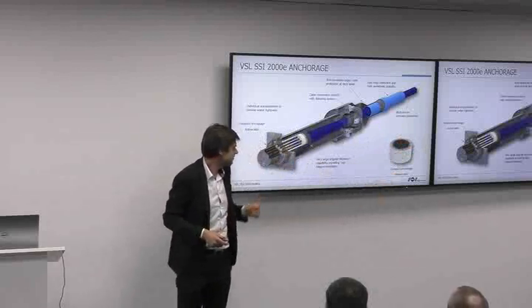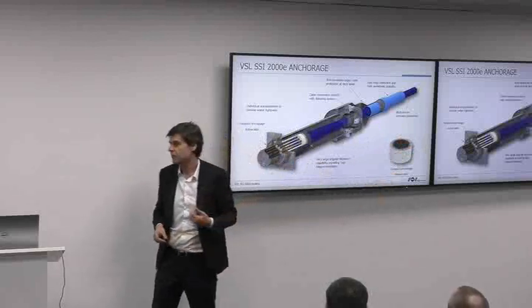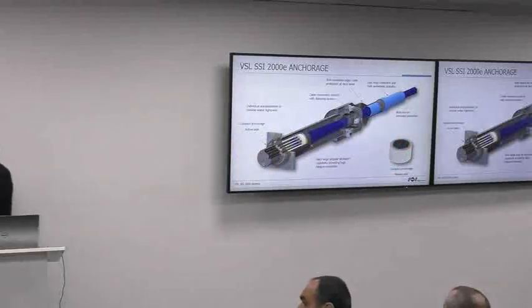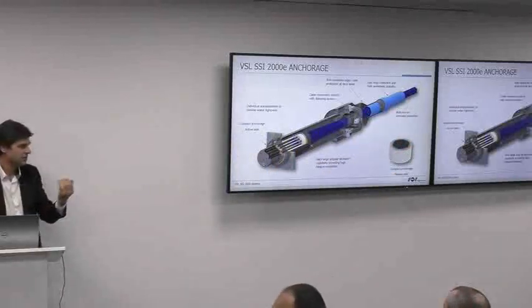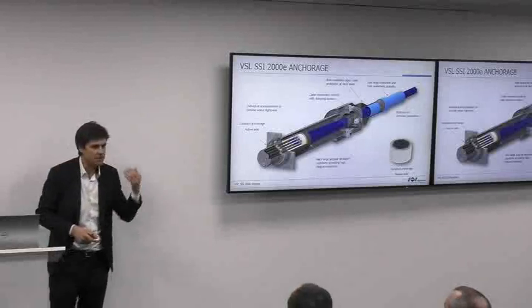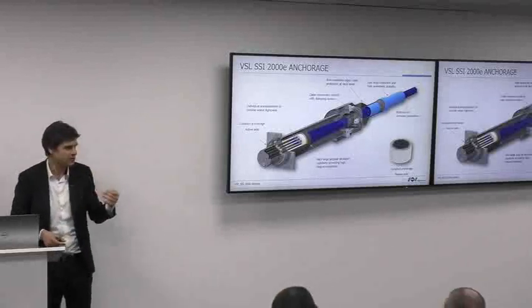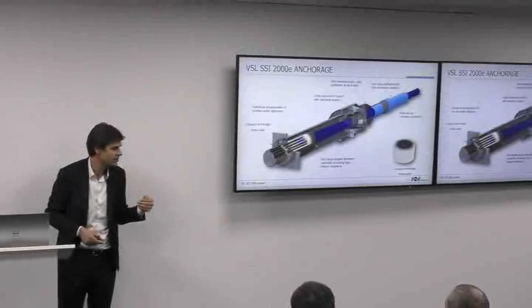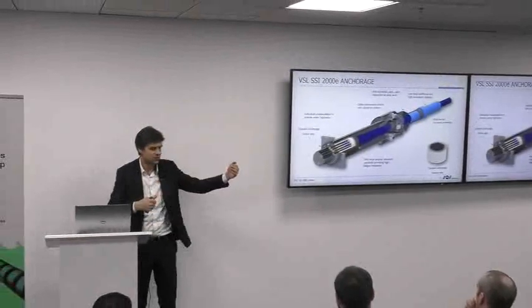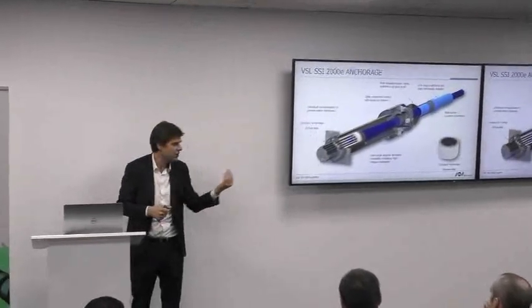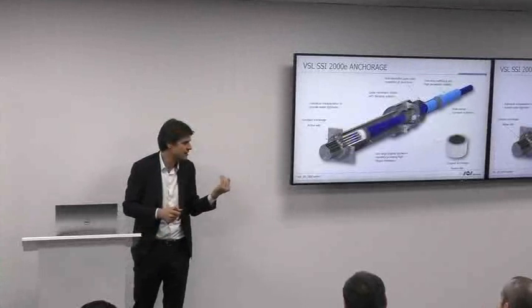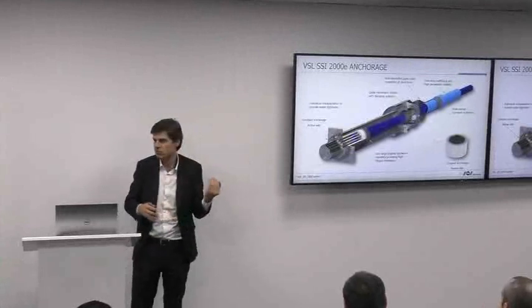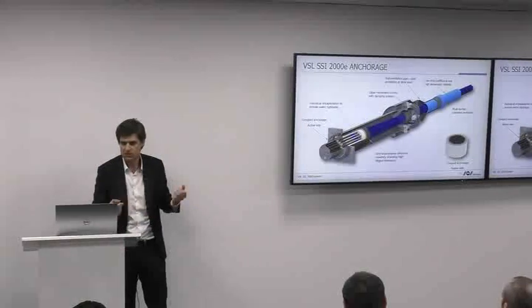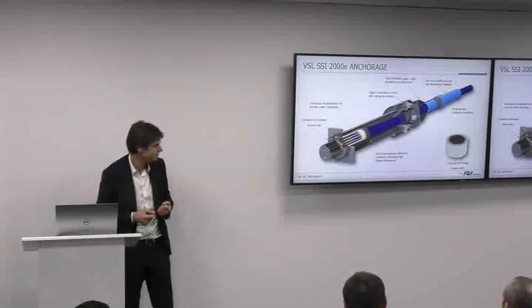This is kept for the active side for one reason, because from this side you have to stress or tune the force of the cable. So there you don't know where stops the sheathing of the strand, and the sheathing of the strand has to stop inside the anchor block. So we have an extension which is required to make sure that we absorb this position of the sheathing stopping inside the anchor head, and to make sure the system remains tight during service and during installation.